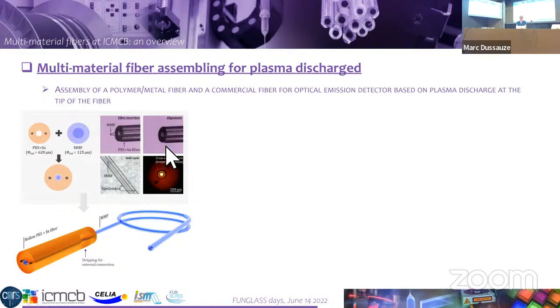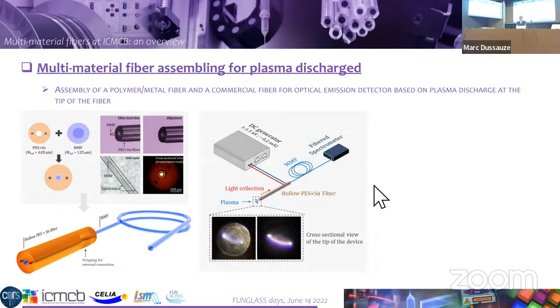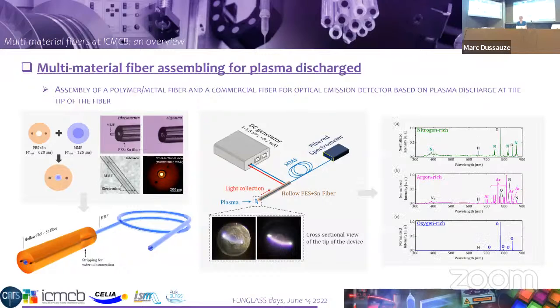At the end, what we get is something that looks like this. We have the assembling of the polymer, the electrodes, and then the commercial fibers in this case. Now we see better here downstairs. And then here, once again, the potential is applied to the electrodes. The plasma is generated, and then we can use the commercial fibers inside to analyze the plasma remotely. And then a demonstration was made using three different atmospheres: nitrogen, argon, or oxygen.